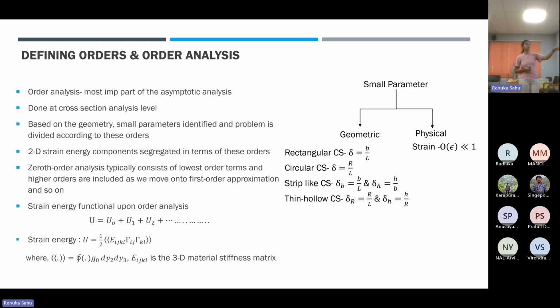Depending on different cross sections, we have listed out the small parameters used. For rectangular cross section, it's B by L, where B is the width of the beam and L is the length. For circular cross section, the small parameter will be radius to length ratio. For strip-like cross sections, where the order of beam width and beam thickness is very different, we'll have two small parameters: width to length ratio and thickness to beam width ratio. And similarly, for thin hollow cross sections, we will have radius to length ratio and thickness to radius ratio as the small parameters. For physical small parameter, we consider the strain as the physical small parameter.